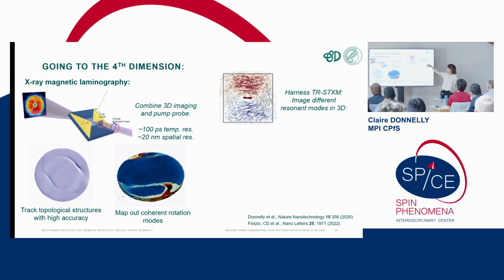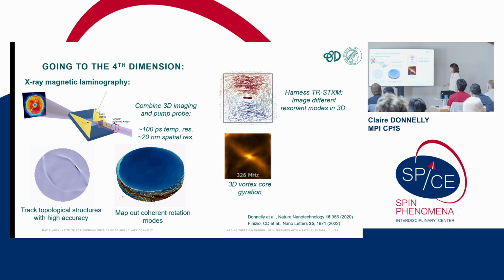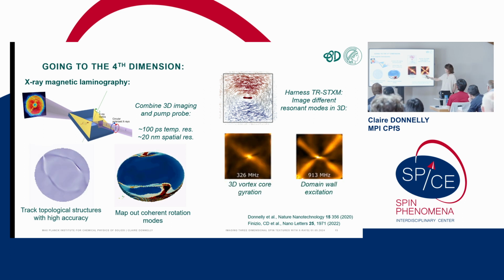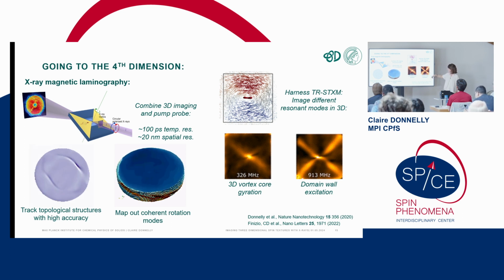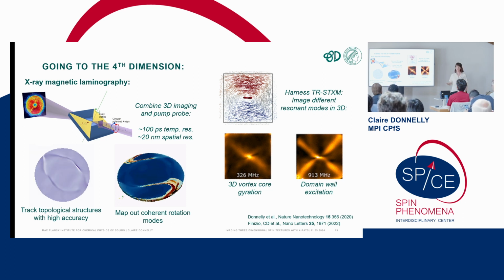And let's say in a nice demo again, we were able to show that we could measure the resonant dynamics of this Landau pattern, tuning to the 300 megahertz resonance of the vortex core, and then the 900 megahertz resonance of these domain walls. And so again, just like we were saying about the topological textures, this potentially opens up the imaging of resonant dynamics in 3D for many of your samples.